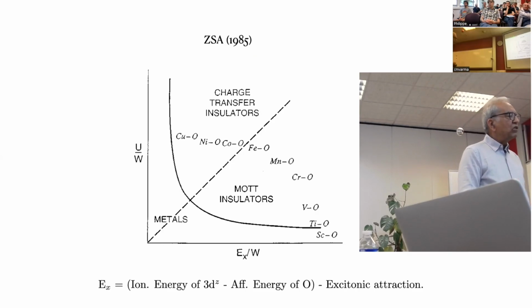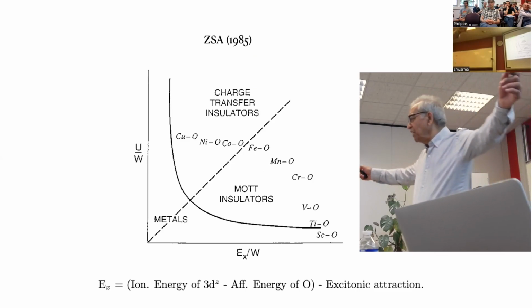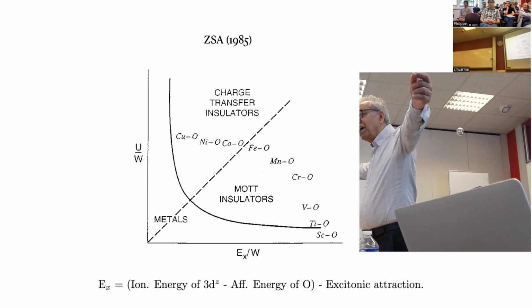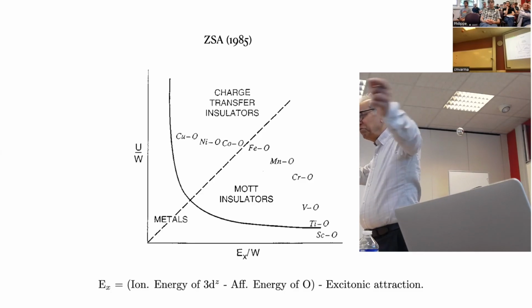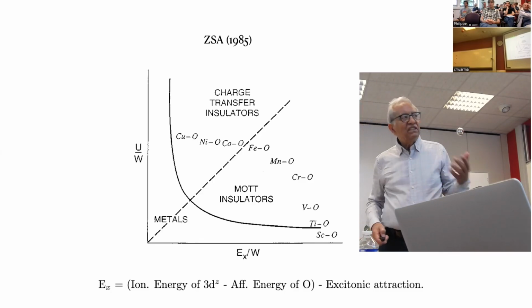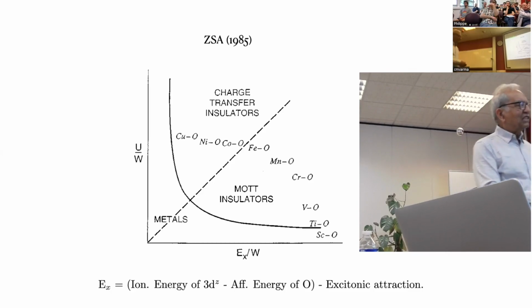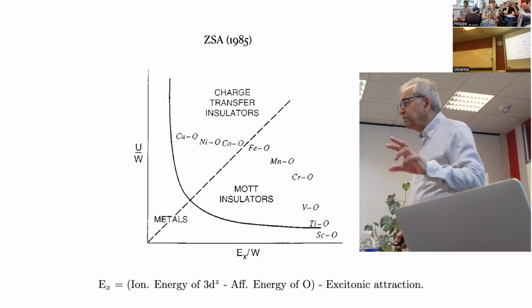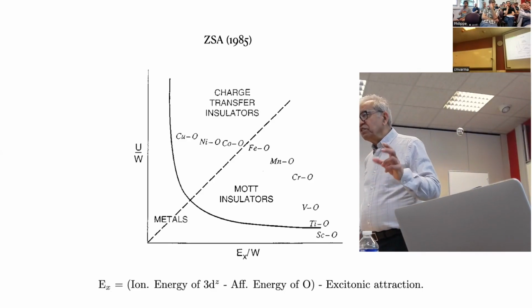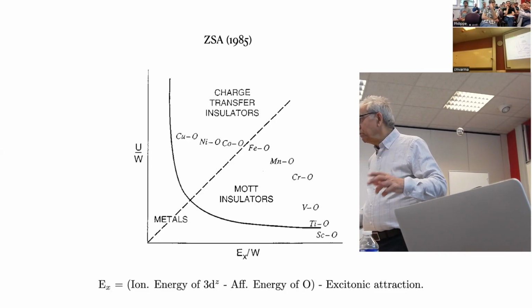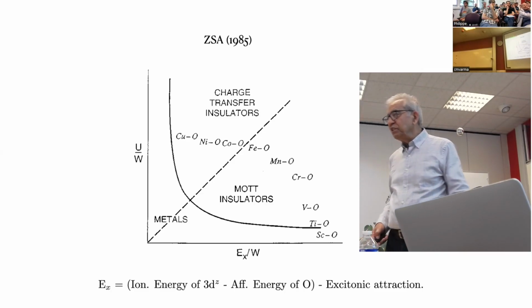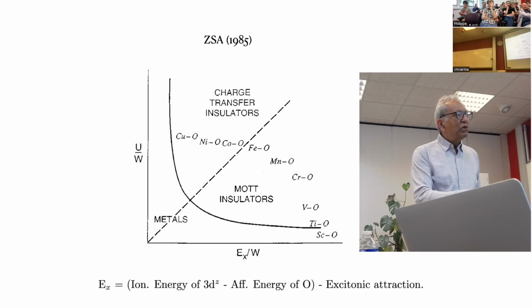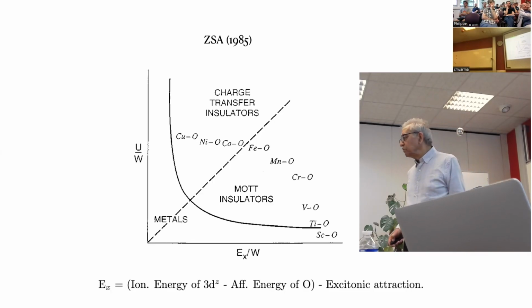There's one important change that I made. This affinity energy and ionization energy are defined with isolated ions, but we are dealing with a solid. And if these energies are close, we have to very importantly include the interaction energy between the copper levels and the oxygen levels. Okay? Because they're going to control the charge fluctuation. This will become an important parameter when this energy difference is small.